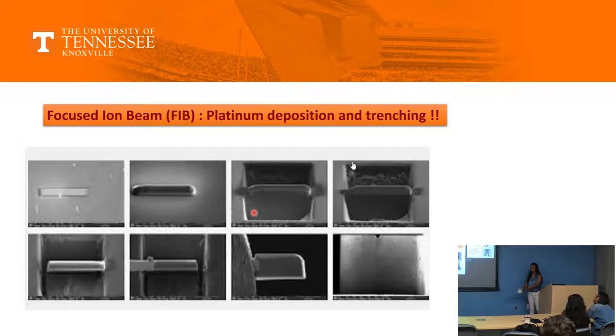This is what you see: earlier it was a flat piece, you have tilted it, and you're seeing these grooves. And you see how deep the sample is. If you don't see them while tilting, that means it's still connected. If it's still connected at the bottom, you go for a deeper trench. In the beginning it looks tough, but till here, till step four, it's very easy.